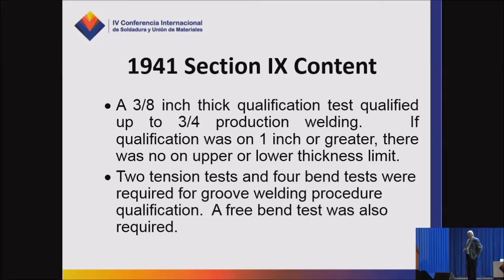But it said that if you qualified the procedure on a test piece that was 1 inch thick, there was no upper limit on how thick a material you could weld. And you might say, good grief, that's not very conservative. Keep in mind, this was 1941. Nobody was building anything that was much over an inch or so in thickness at that time.